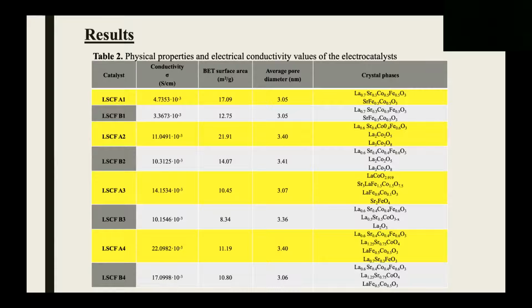And here, all the samples marked in yellow have a higher specific surface area compared to the version calcinated at 900 degrees Celsius. And this correlation is also relevant for the conductivity results, actually. The catalysts which were calcinated at 800 degrees Celsius have a higher electrical conductivity compared to the catalysts which were calcinated at 900 degrees Celsius.